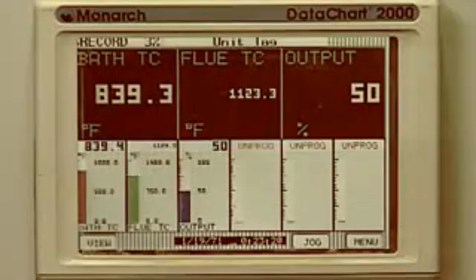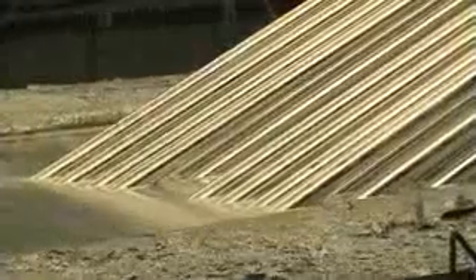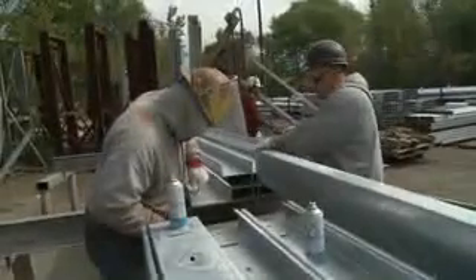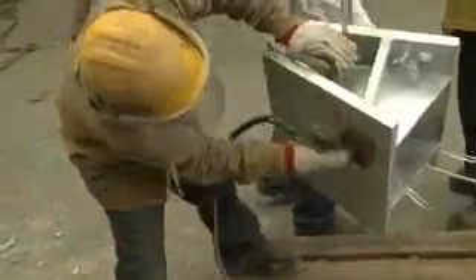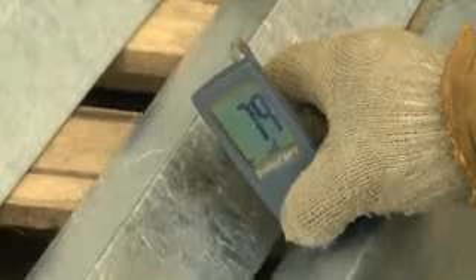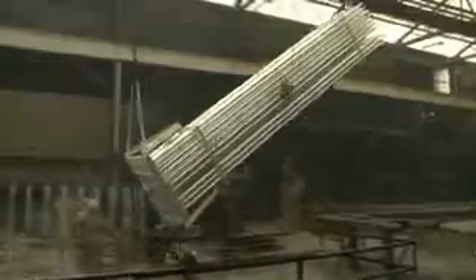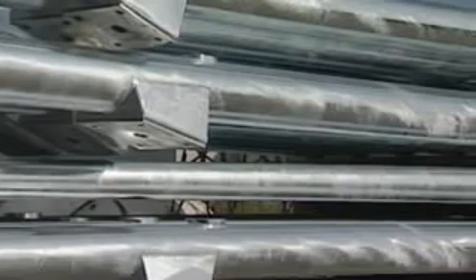The 98% pure zinc bath is heated to 830 degrees Fahrenheit. While in the kettle, the zinc metallurgically reacts with the iron in the steel to form a series of intermetallic layers. After the steel is removed and cooled, it is inspected to check the zinc coating thickness and appearance. Any sharp grips or spikes are removed, and the thickness is measured. The final look of the galvanized coating can vary from piece to piece. The appearance is determined by steel chemistry, zinc bath composition, and cooling rates. Whether bright and shiny or a matte gray, the final visual appearance does not affect its corrosion protection.